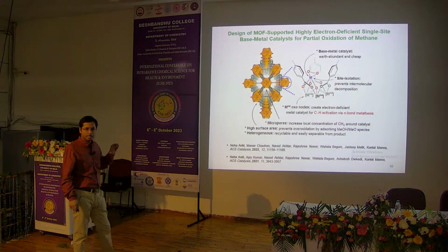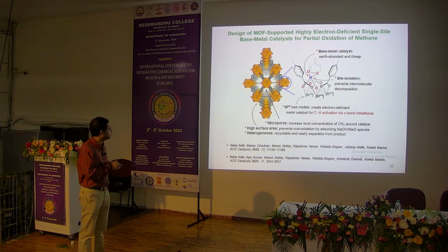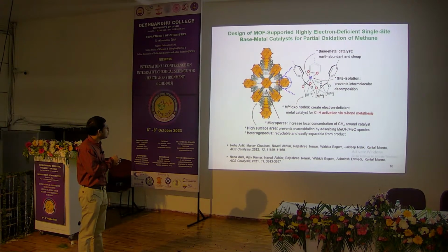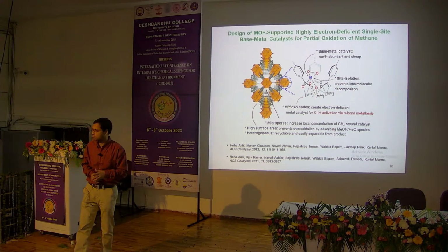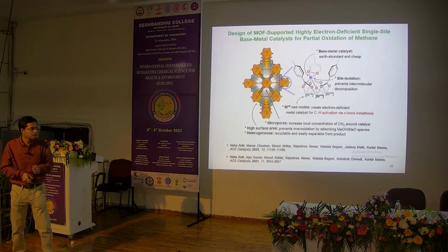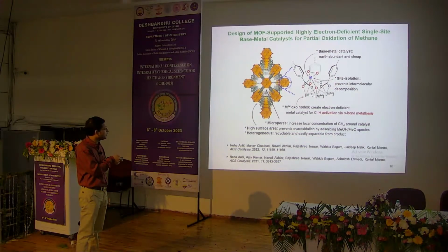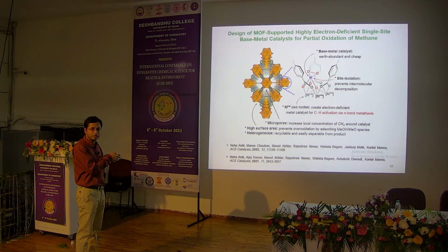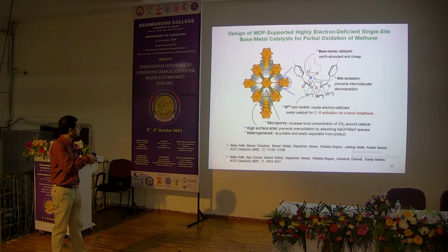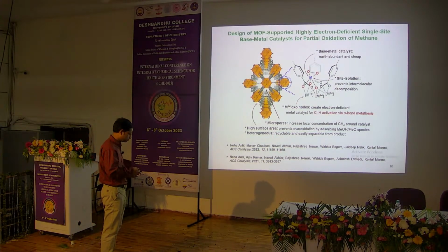To develop single site earth abundant metal hydride, oxo, hydroxo, or peroxo complexes at the node of a metal organic framework, where the nodes are composed of high valent metal ions, suppose zirconium 4+, hafnium 4+, cerium 4+, because these metal oxo nodes will be highly electron withdrawing. It can make the metal center highly electron deficient, so that methane can be activated via sigma bond metathesis. Not only that, there are many other advantages of using MOFs that I listed here.